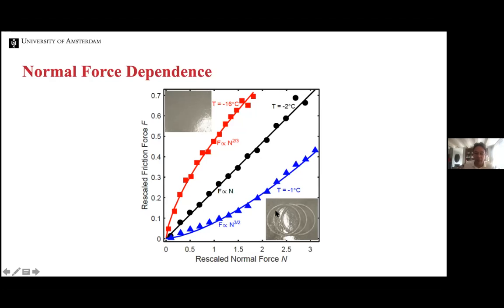But what is more striking is that you see that the ball, if you go close to melting, actually leaves a circular trace in the ice. So basically, you're no longer skating on the ice, you are plowing through the ice, and that's where the 3/2 comes from. If you go to very high temperature, you actually get the result for Hertz contact, because you have a sphere on a flat plane, and for a sphere on a flat plane, you would expect this 2/3 power. So low temperature, no trace, and bona fide skating. High temperature, you leave a trace, and so you're no longer skating, you're actually plowing. So you go from elastic to plastic, if you like.